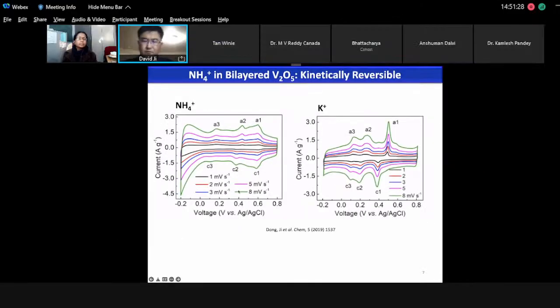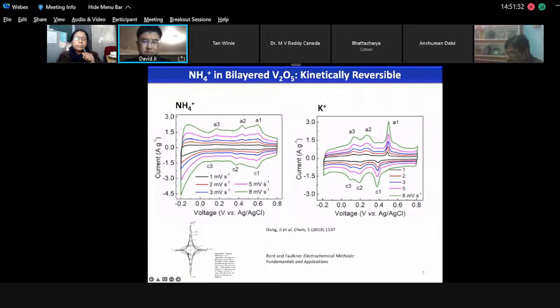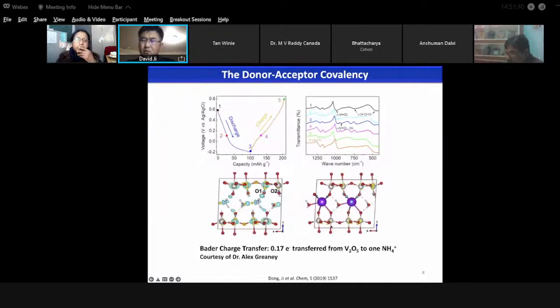And then we realized something afterwards. So this is the typical explanation. You can find such behavior in a well-known Bard and Faulkner's book, right? So we find something with ammonium ion inserted. You have this vanadium oxygen vibration completely transformed. It's split into two peaks for each of them. If you insert potassium ions, you don't have that phenomenon. So the peaks won't split. So the splitting of the peaks is telling about directional bond. So you have directional bond of the charge carrier with the host, and directional bond is typically covalent interaction. And potassium obviously cannot do that. Potassium is ionic.